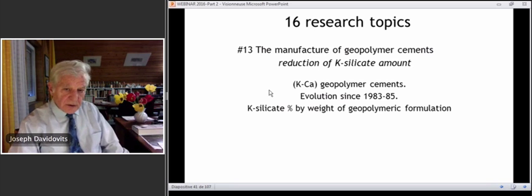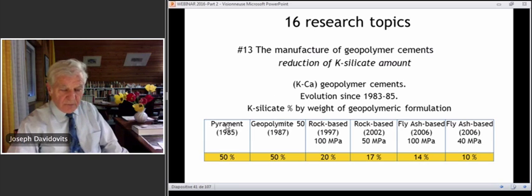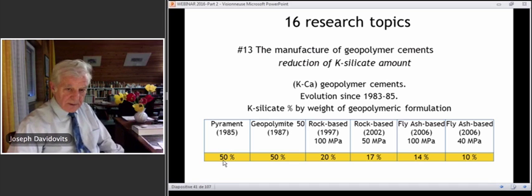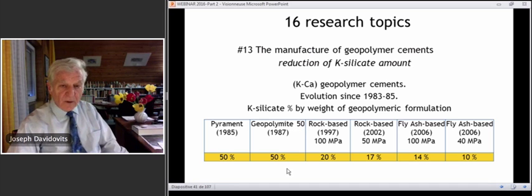If you look at the reduction of the potassium silicate or sodium silicate amount from the beginning, that is since the invention in 1983, 1985 in Lone Star, the first Pyrament, we had 50% silicate in it. In the first Geopolymite 50 that was used for the toxic waste and mine tailings waste management in 1987, 50%, and then we started to diminish the system because we understood that we had to diminish the quantity of the silicates in order to start mass production.